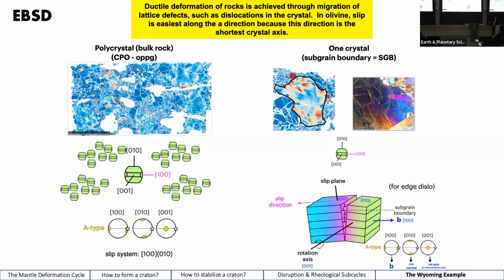And when we do EBSD data on xenoliths, the skeptical structural geologists here should be worried about how do we even know what direction corresponds to a shear direction, right? Because a xenolith is like a meteorite. We have no kinematic reference frame. Whereas if you go to an outcrop and you measure a shear zone, you know the absolute reference frame. So olivine is also helpful here because thankfully with its orthorhombic symmetry, we have a very predictable